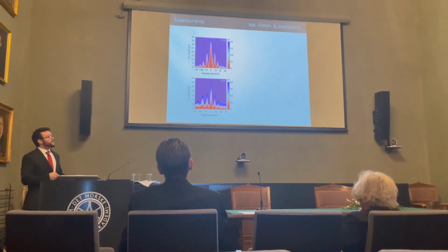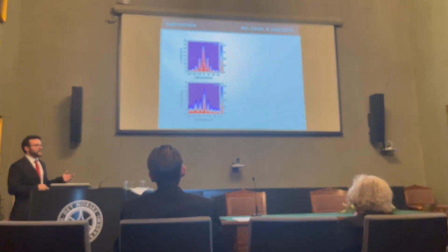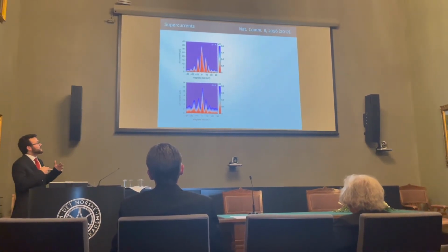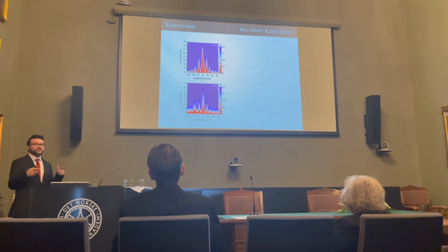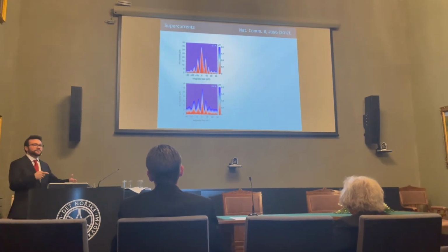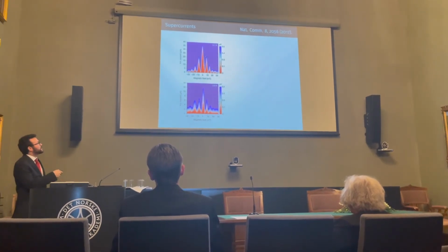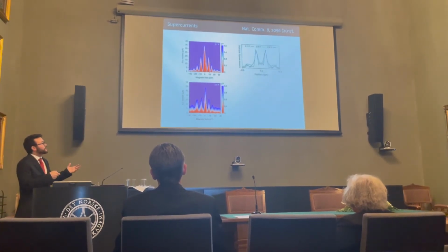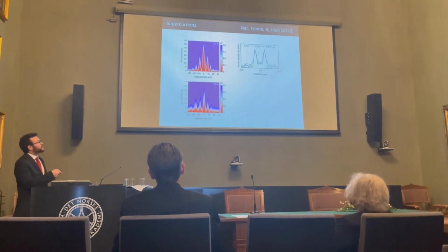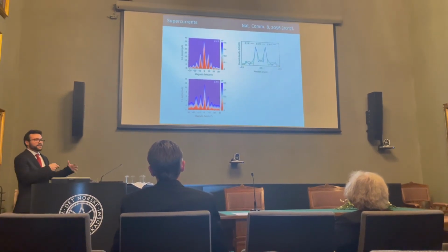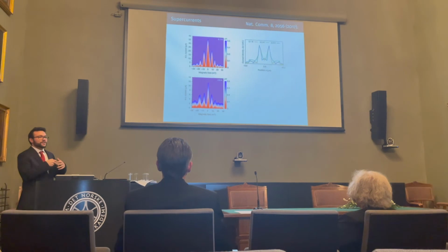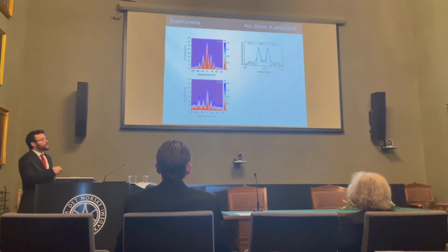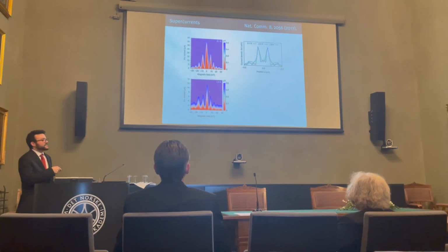So in their experiment, they then did something called a quantum interference experiment, where they basically checked the electric current flowing between the two halves of the superconductor as a function of an applied magnetic field, which gave some figures that looked like this. Then we helped them associate this to theory and find out basically exactly where in their system would the supercurrents have to flow, which is, here's the spatial distribution we found, in order to produce the observed interference experiments.